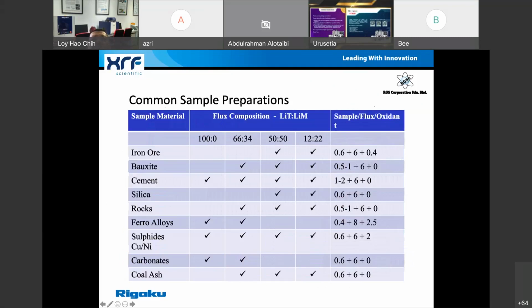And this is a common sample preparation table. Let's say today you have bauxite samples and you want to fuse them. I can fuse them with 66/34. Many different fluxes can also be used, as you can see in the table. And either 66/34 or 50-50, these two are actually quite common. Most samples can be fused with these two formulations.